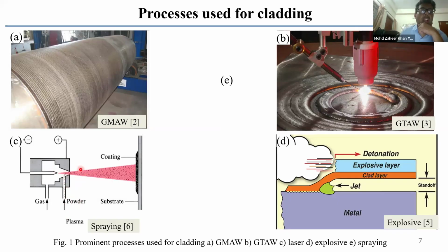So when this is coming out at a high velocity, there will be a negative pressure or a vacuum created, which will be sucking the powder inside. The powder will melt in the form of tiny droplets. It will be propelled through this gas, and it will be depositing on the substrate in this form. So this is another thermal spraying process that can be used.